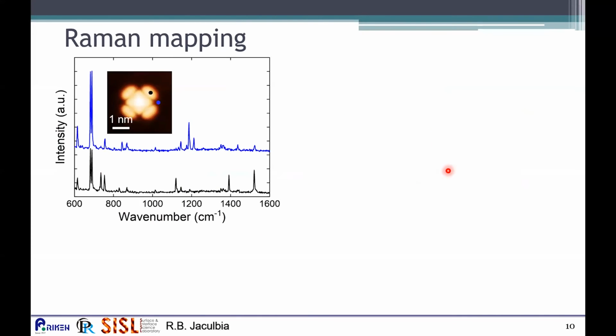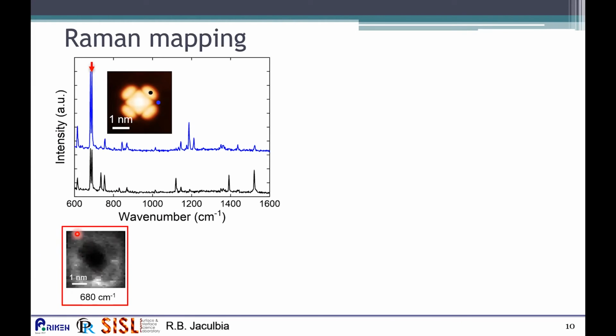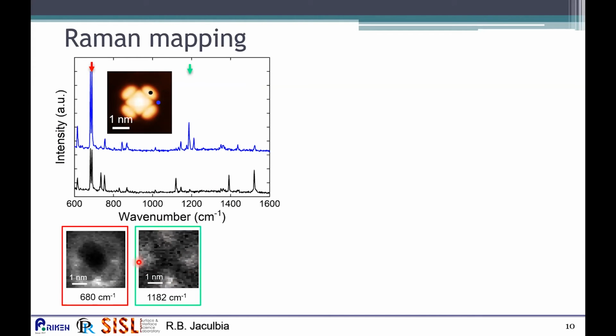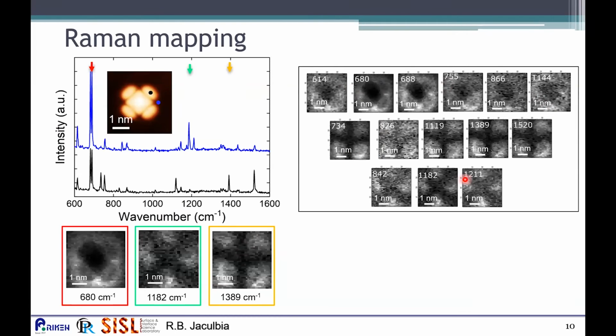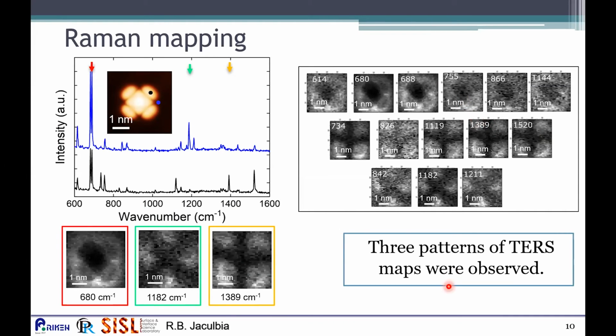Under these resonance conditions, we also tried to perform Raman mapping, wherein we measured the Raman signals of our molecule by placing the tip around the molecule. When we perform the Raman mappings and look at certain peaks, for example this peak, we observe such a Raman map. The Raman signals are intense at this circular region. On the other hand, for this peak, we found that the Raman signals are only strong at these four positions. Lastly, for this peak, we found that the Raman signals are only strong at these four positions. And when we check all the Raman maps with good signal-to-noise ratios, we found that there are only 3 patterns of the Raman maps: circular, cross, and plus.